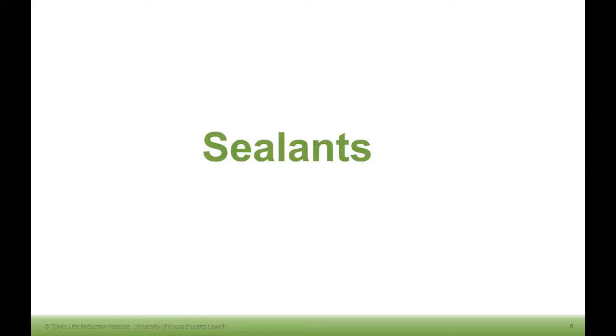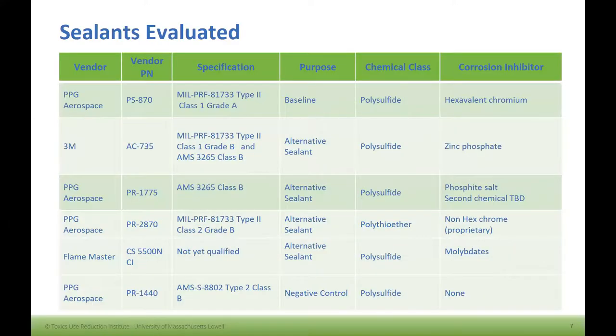So the first application we'll talk about is sealants. We looked at six different sealants, and we had one as a baseline to do the comparison against. That was the PS870. Then we had four alternative sealants that had a variety of different types of corrosion inhibitor chemistries. And then we had a negative control, which was a sealant that didn't have any corrosion inhibitor. We put that in there to make sure our experiments were working correctly, because if the one without corrosion inhibitor worked the best, we knew we had a problem. So those are the six sealants that we included.